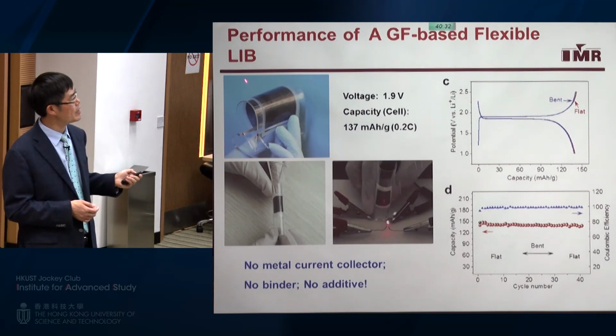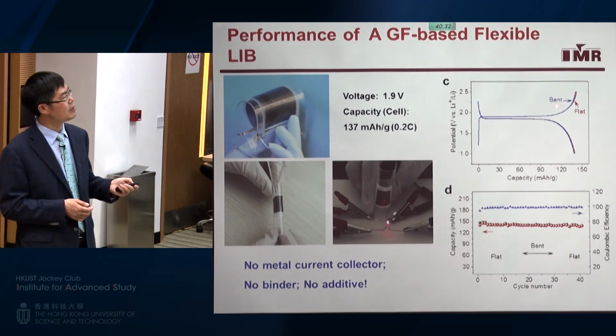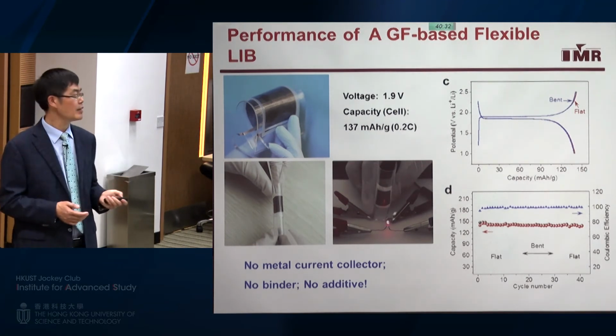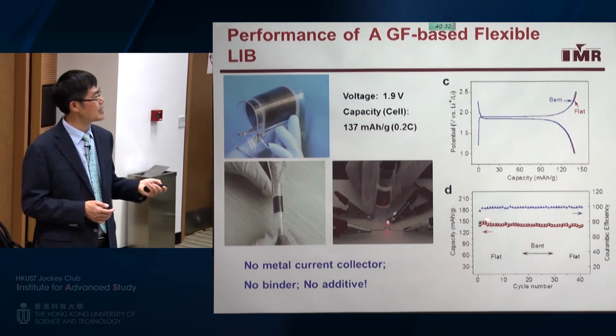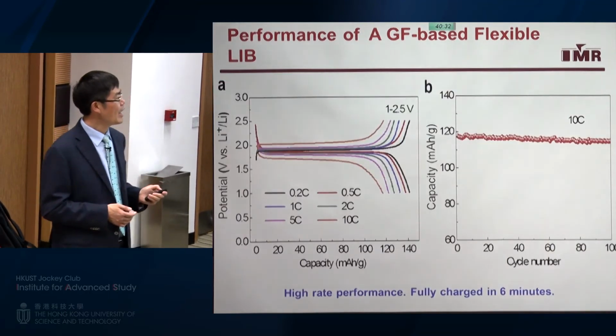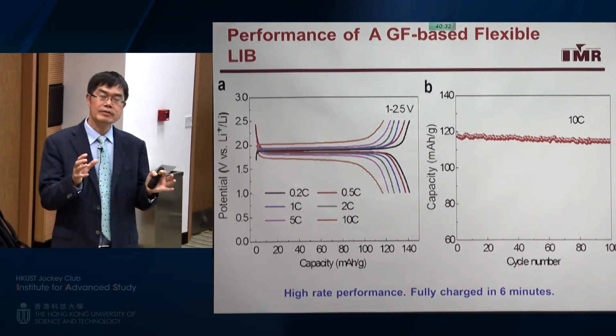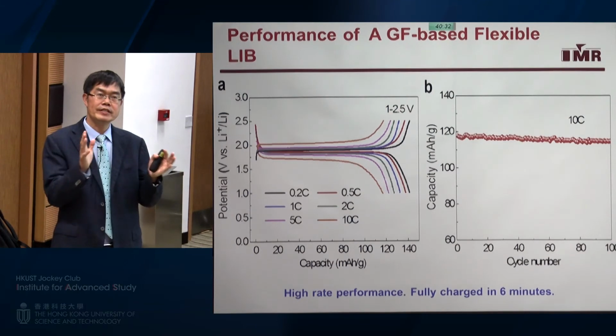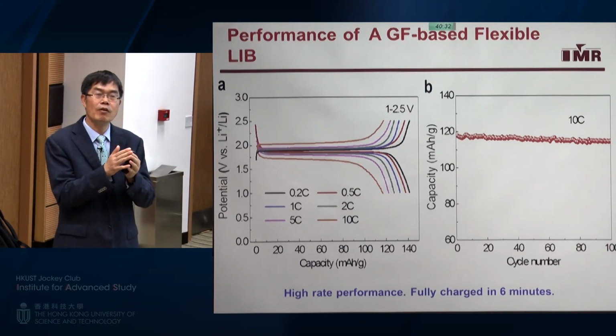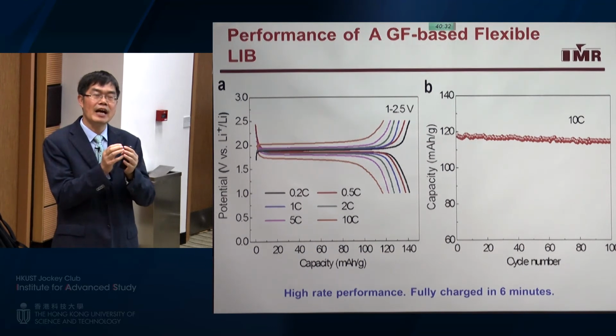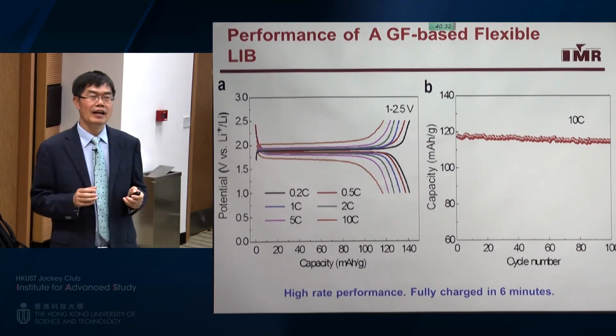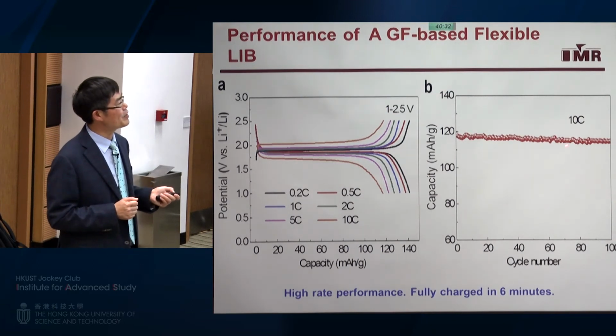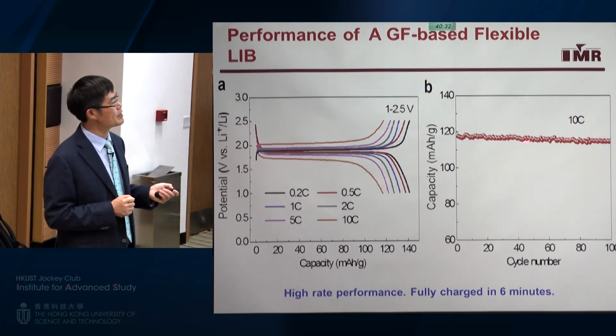This is a flexible lithium-ion battery, which has very good electrical conductivity in both bent and flat states, and also very good cyclability, as I show you here. Because the active materials are very well incorporated into the graphene foam, with close contact, the rate capability is very good. As I show you, at 10C, which means 6 minutes charge, we can have very stable capacity.